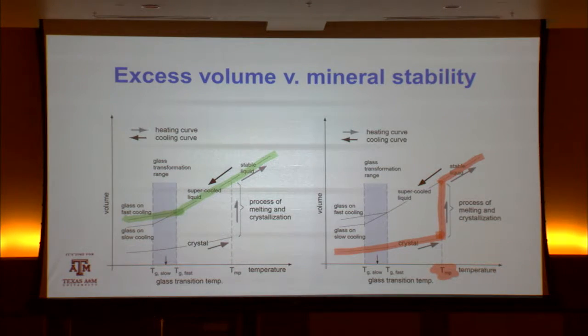When molten material solidifies, it goes through a cooling process. So this is temperature, and here's the melt temperature up here. As the temperature decreases as it cools, if that occurs at a rapid rate, then there's not enough time for those basic building blocks to organize themselves in a low energy state. Not enough time. So they are disordered. They're amorphous. On the other hand, if the cooling rate is slow enough, then they can ultimately lock themselves into position, coordinating to positions that lower their free energy and making them crystalline in nature.